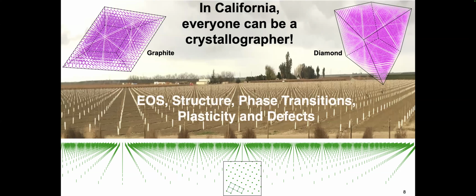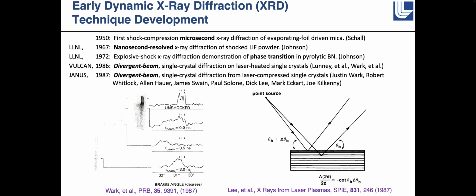And from this crystallography and from the diffraction that I'm going to talk about, we can measure the equation of state, the stress and density. We can measure the structure of the phases. We can measure transitions between different structures, and we can look at how rapidly these transitions happen, and we can measure many properties of these transitions, and we can measure plasticity and defects in the materials. So I'll talk about all of those.